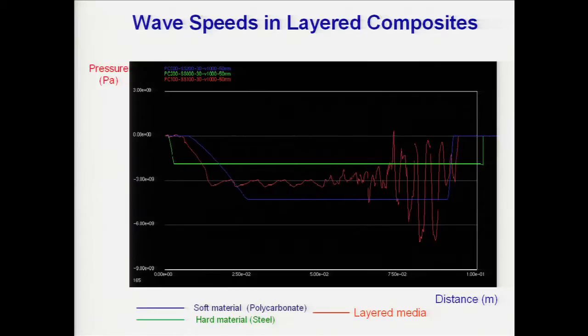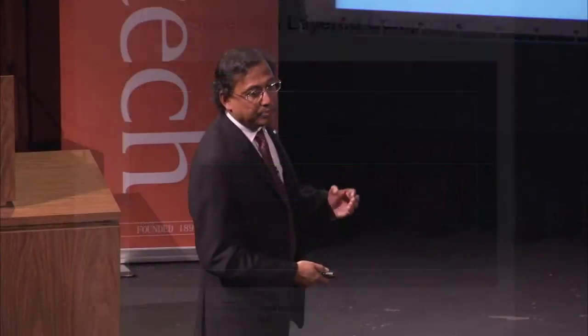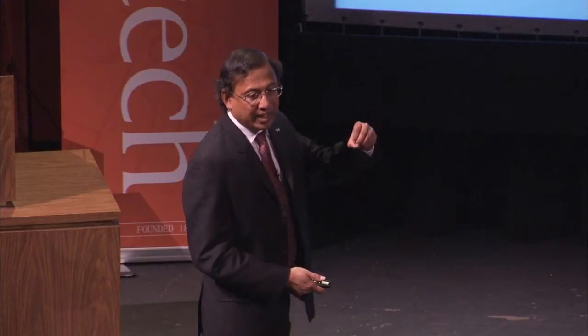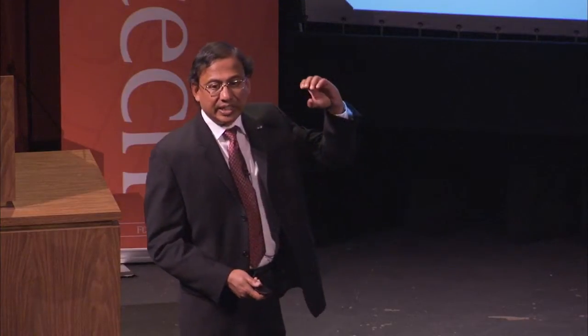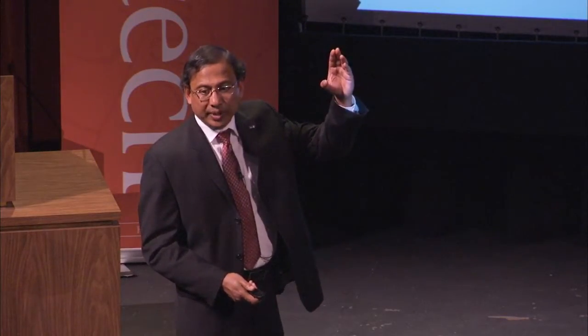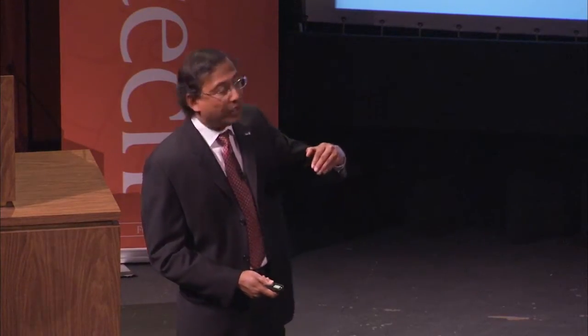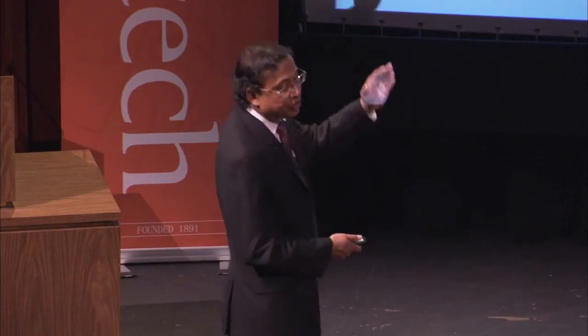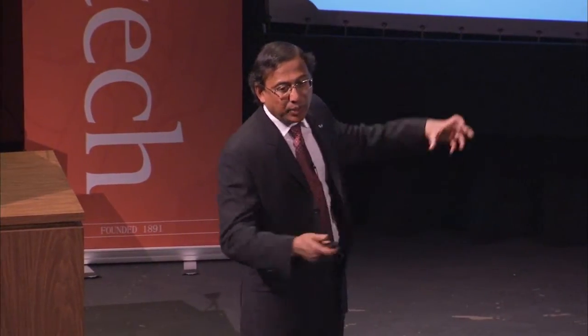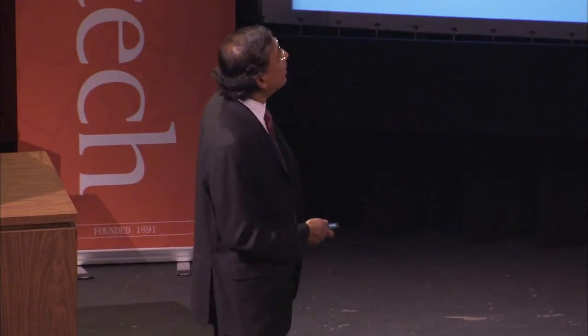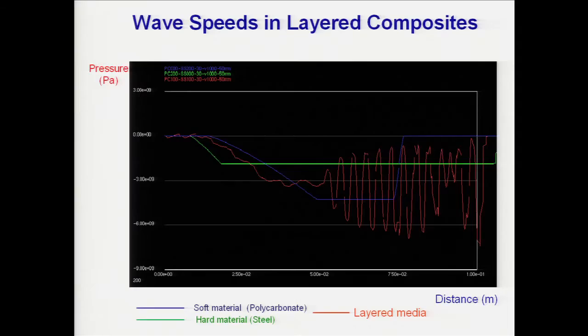So when it is propagating slower than the other two, that means the shock wave speed is smaller, which I mentioned to you earlier, that the pressure is proportional to the shock wave speed. And so you can already lower the pressure. And also, there are these oscillations which cause the dispersion of the momentum which you are imparting to the structure. So this is one of the basic ideas behind bulletproof glass, or if you want to create a very effective armor for dispersing momentum.